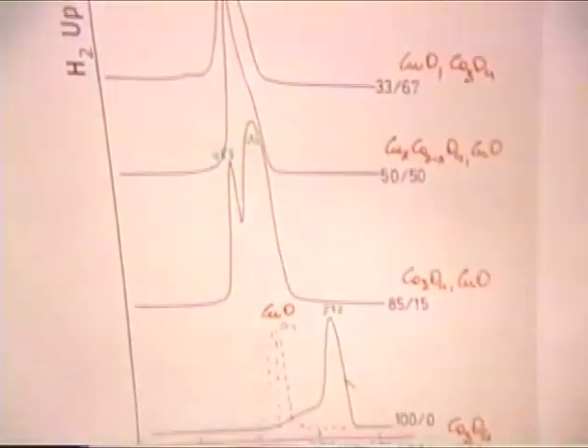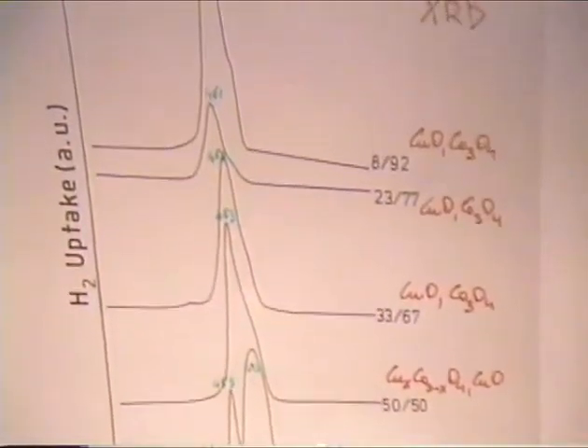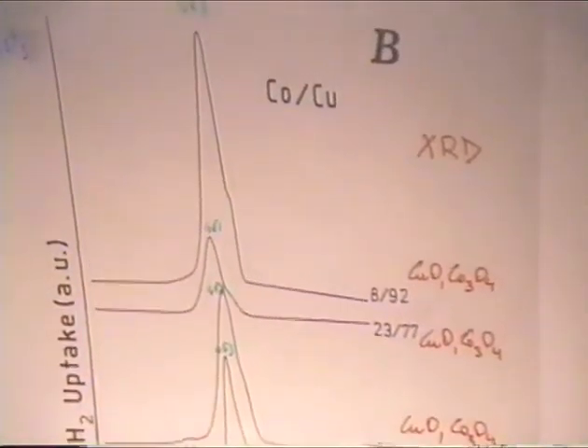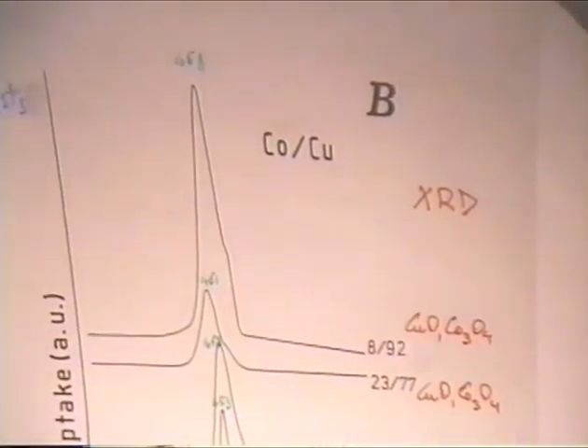Now the situation for the air-calcined catalysts. The TPR results of the air-calcined catalysts are reported in this transparency. The reduction profile of the pure Co3O4 is characterized by a shoulder at lower temperature and by a main peak located at about 600 K.